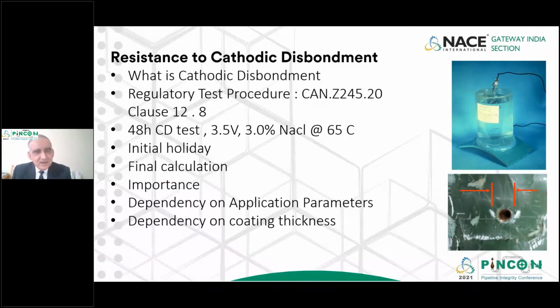The second parameter is resistance to cathodic disbondment. Again, a very important parameter for coating. In the picture, a piece of pipe is taken at the bottom, and a plastic or glass beaker is built on it using a sealant. An intentional holiday is created. A holiday means a small incision: a small circle is intentionally cut using a knife, and the guideline says it should be 3 millimeter diameter. There is an electrolyte solution, which is 3% sodium chloride and water. Then an electrode is attached through the electrolyte, typically a calomel electrode.